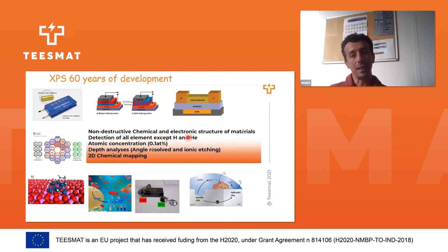It needs either very simple interpretation or advanced interpretation through ab initio calculation. We can detect all elements except hydrogen and helium. We can get atomic concentration. The sensitivity of XPS is 0.1 atomic percent. We can perform depth analysis either by angle-resolved measurements, ion etching, or gas cluster etching. I didn't show you this example. We can also do 2D chemical mapping, mapping the chemical structure.